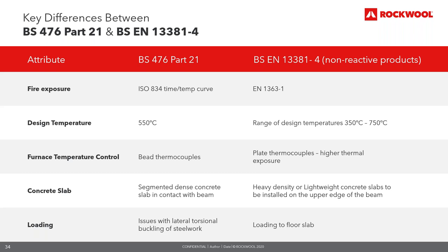The change to a plate thermocouple is designed to harmonise the exposure of furnaces across the EU, and it results in a higher thermal exposure compared to the British standard, therefore a more onerous heating regime. Plate thermocouples represent a large area to the furnace, which responds much more slowly than the smaller bead thermocouple. Consequently, to get the plate thermocouples to respond quickly requires inputting significantly greater amounts of energy into the furnace than is required when it's controlled by a bead thermocouple, especially during the first 30 minutes of exposure when compared to the BS test regime.